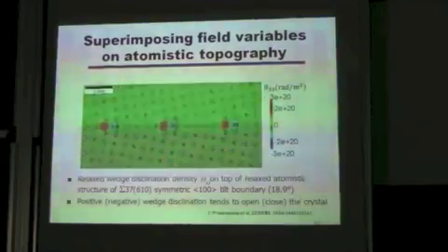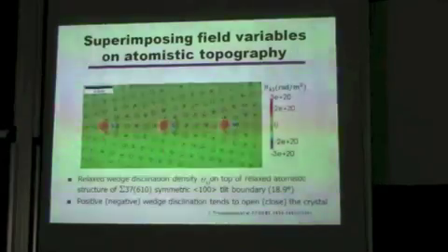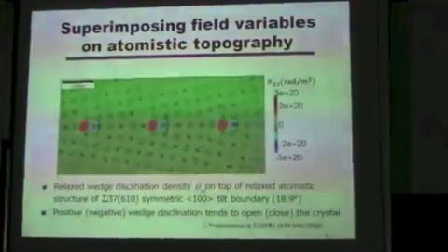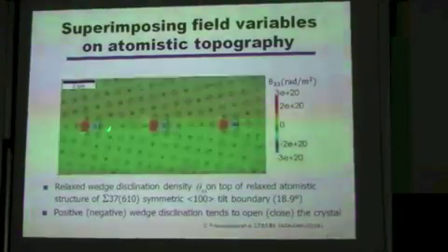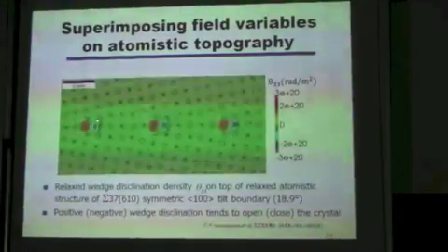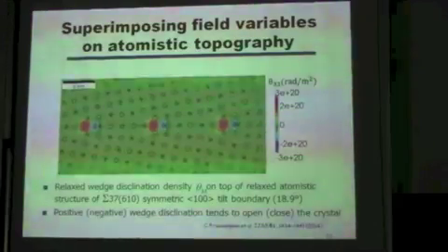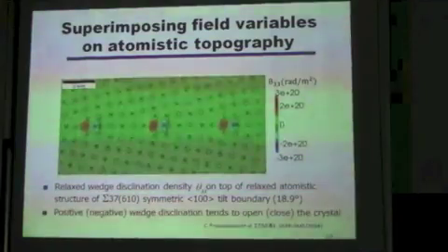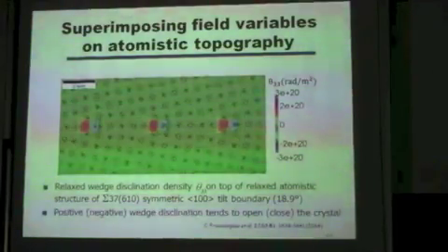So again, you have here what we found from the continuous theory, and the background is the atomistic representation of the same tilt boundary. So you have here one dipole of disclinations and two other ones. You can see that they fit perfectly with what is called the structural unit, the atomistic structural unit, which is constitutive of the grain boundary in the atomistic representation.